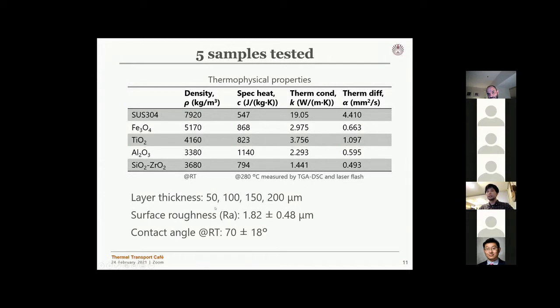We also tested different thicknesses, from 50 microns to 200 microns. As for surface roughness, we didn't see much variation, so in this study we've ruled out the effect of roughness. We also measured contact angle at room temperature and found it to be about 70 degrees, with rather limited variation, so we've ruled out the effect of contact angle too.